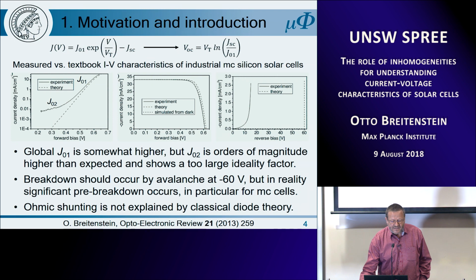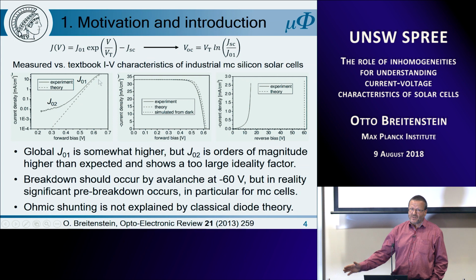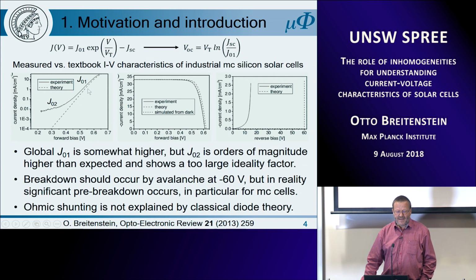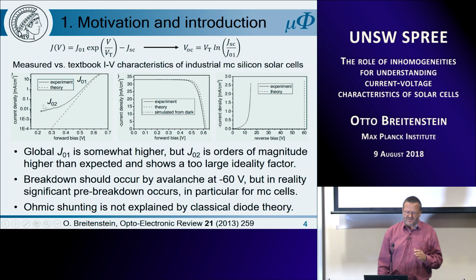If you look at the dark characteristic, the dashed characteristic is the expected one according to this, and the drawn characteristic here is a really measured one. This was modeled by PC1D, which is also a homogeneous solar cell model, to reflect the data of this solar cell. And we see that the global J01 is somewhat higher than expected, but J02 is orders of magnitude higher than expected and has a too large ideality. So the shallower the slope of this J02 branch, the higher is the ideality factor.